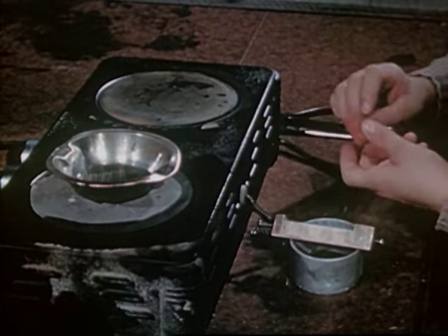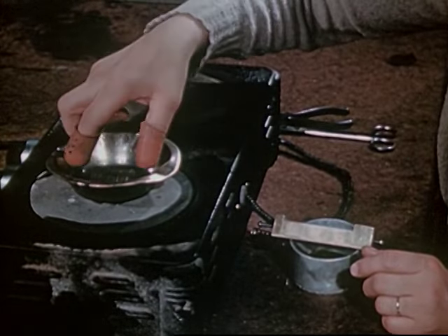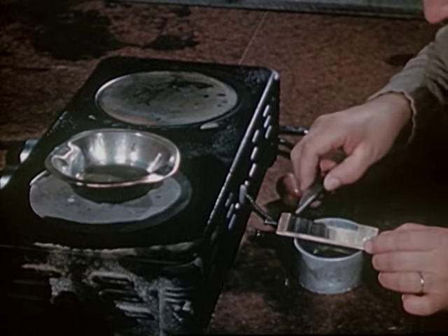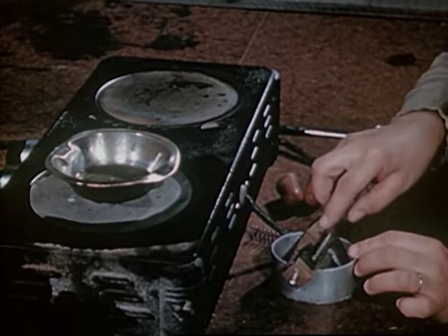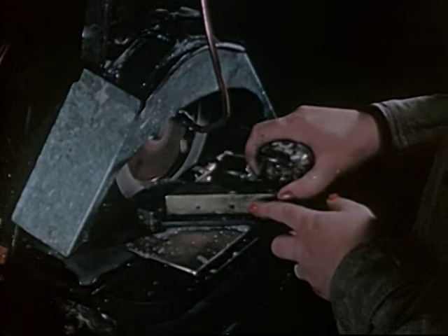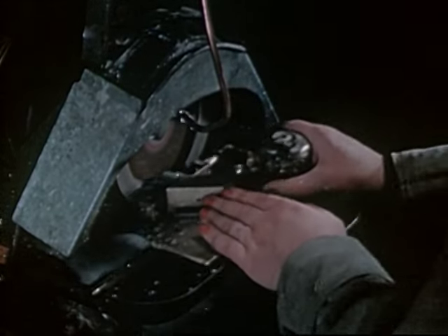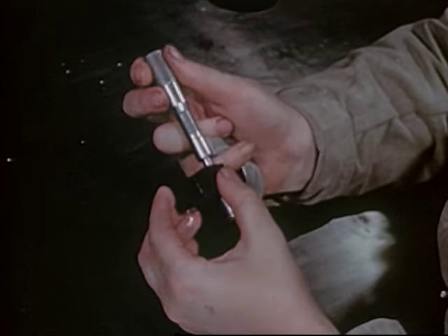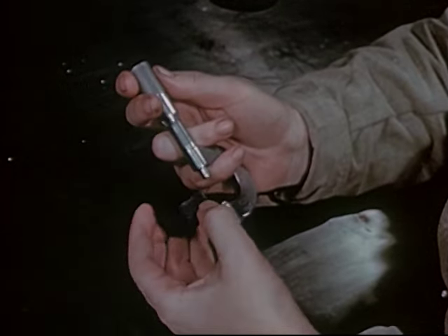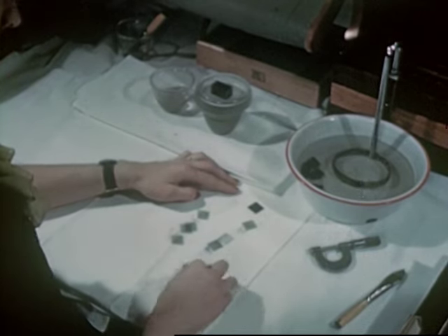In grinding edges to uniform size, the blanks are again stacked in bundles and cemented together with paraffin. The four edges of the stack are ground until they are smooth and even and have the desired dimensions. The blanks are uncemented by soaking in boiling water, then they are cleaned and ready for classification.